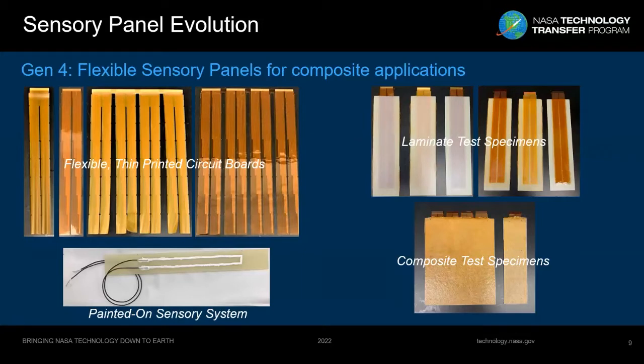The main difference between these two is the thickness. The ones that are a little bit lighter color are about a 32nd of an inch. They're really thin, 32nd of an inch thick or thinner. And the ones that are a little bit darker are slightly thicker. These are polyimide substrates that they're printed on.